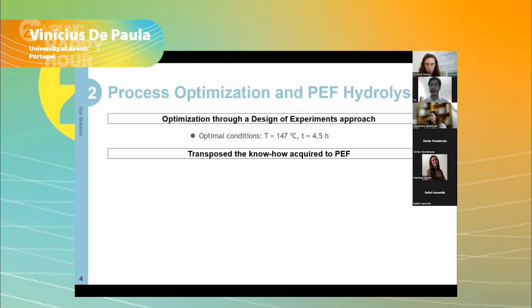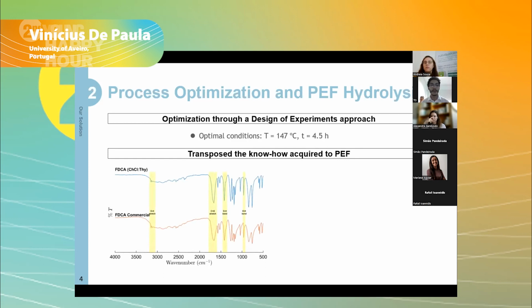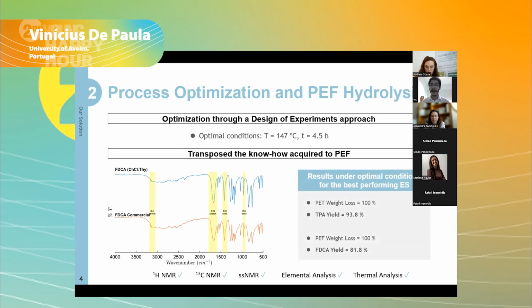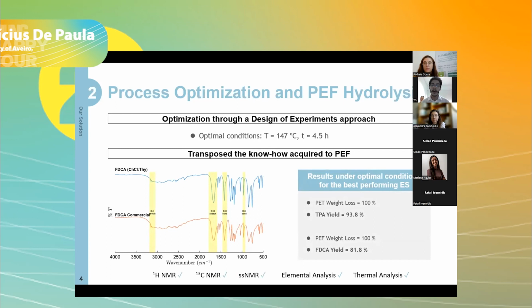And of course, this wouldn't be a Fur for Sustain happy hour if we didn't transpose the know-how acquired from PET to the homologous PEF. Once again, the characterization of our product from this depolymerization of PEF also confirmed that we had our FDCA at the end, so the depolymerization of PEF was also successful. Regarding the yield, TPA was always above 90%, and FDCA always above 80%, which is overall pretty good results.